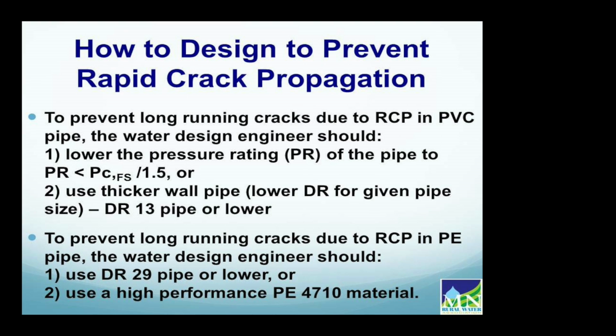So how do we prevent rapid crack propagation in polyethylene? The best way to design against RCP occurrence in PE is to select a material with very high resistance. Most polyethylene materials do have very high resistance to RCP. The critical pressure is generally higher than 1.5 times the leak test pressure. As long as your critical pressure is higher than 1.5 times the leak test pressure, RCP will not occur. With the 4710 materials, it's so high it will never occur.